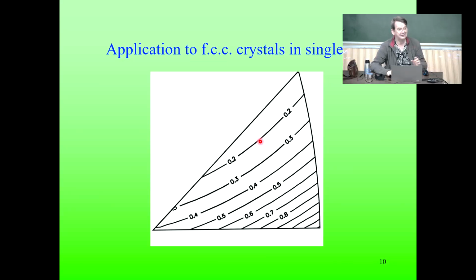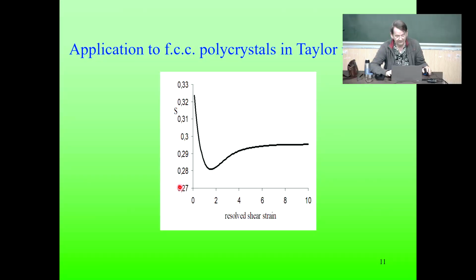Now, considering in which direction the crystal is rotating, you can see what the tendency is. Is the deformation going to be more stabilized by the orientation change or not? So for tensile testing in this diagram, grain orientations go either here or there. So basically it is decreasing. The instability parameter decreasing means that you have better stability. The result is that grain rotation is producing better stability for these single crystals.